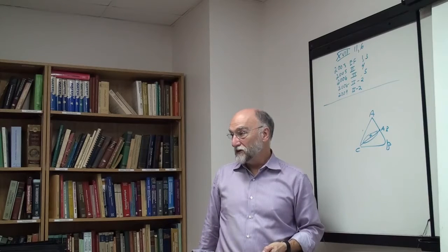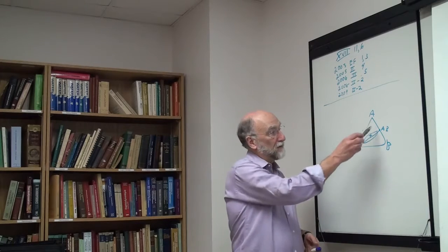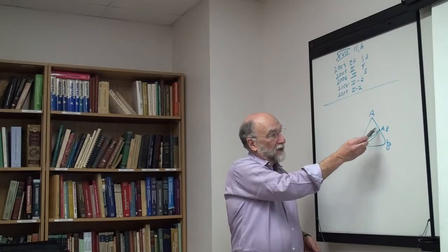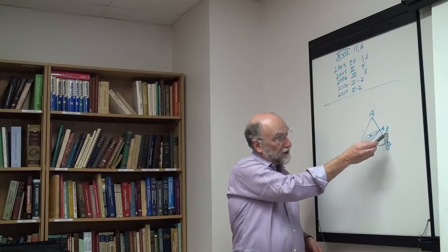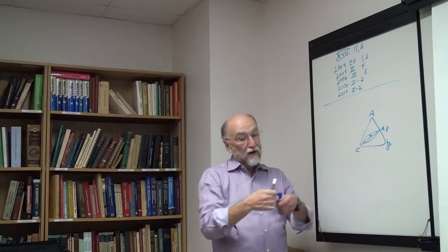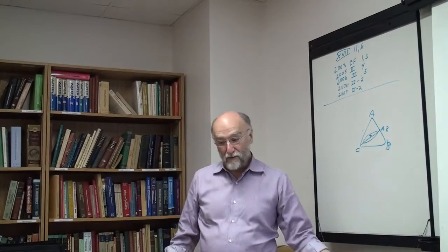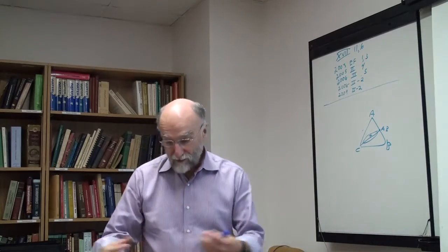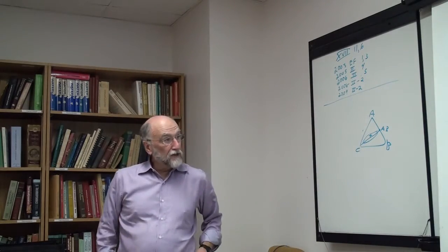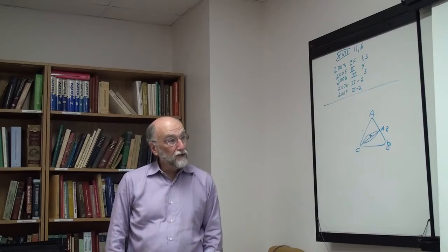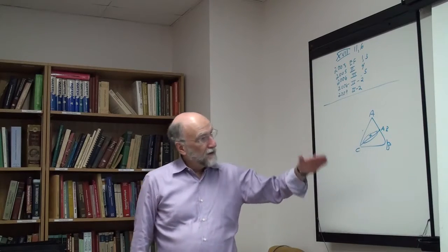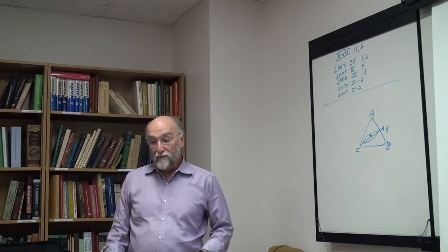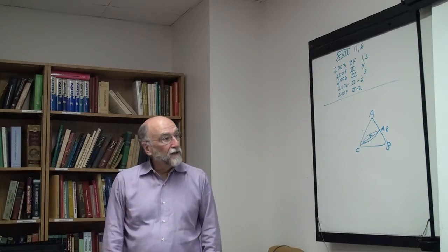to the Gibbs energy. Okay, so if you have strong complexing here, by adding C to the AB, you're breaking up the AB bonds, which are strong, so the AB bonds prefer not to be broken up, so this gives you a tendency to demixing. If the positive deviations are strong enough, you will actually get a miscibility gap along that line, the two-phase region.